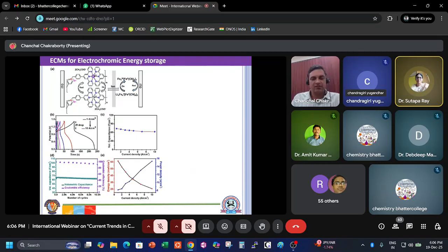Okay, so the electrochemical energy storage property also was studied. In the energy storage studies, we studied the supercapacitor property at defined current densities, and we evaluated the volumetric capacitance to be around 70 at 1 ampere per centimeter cube current density. So this color change is also associated with this energy storage, and we have established that.